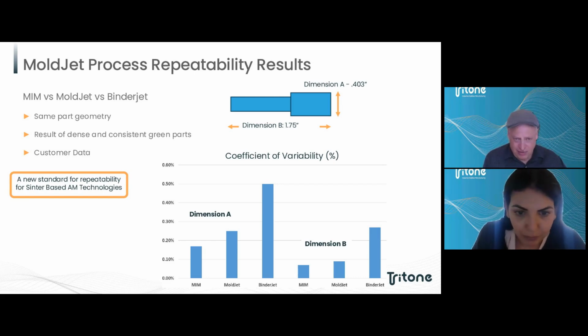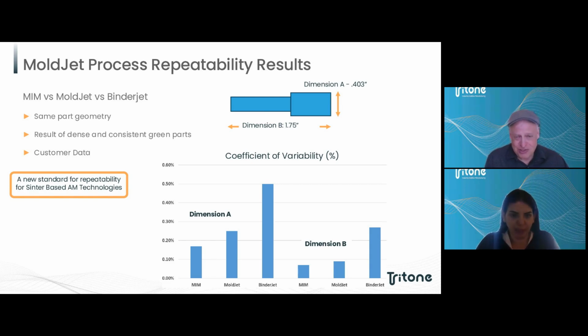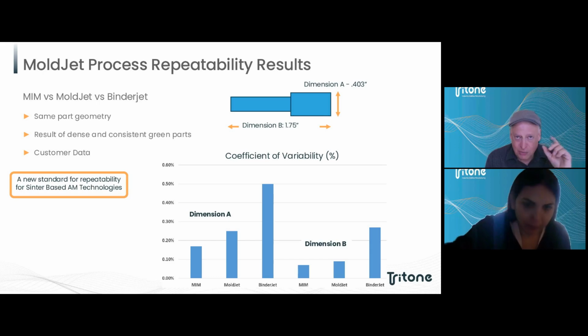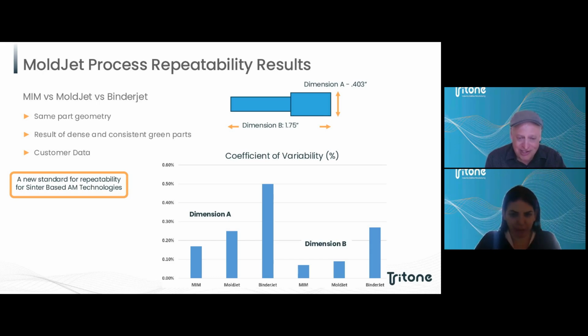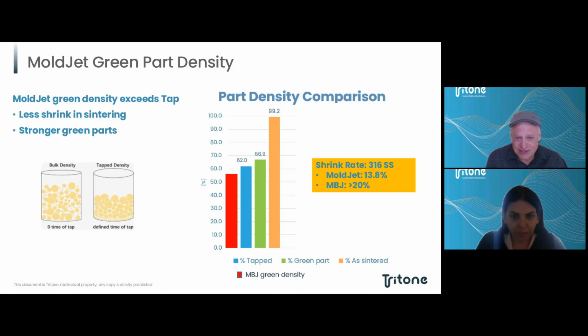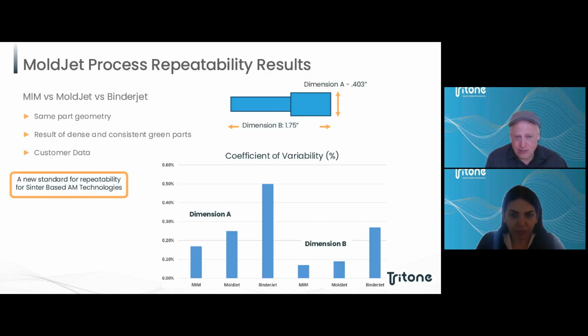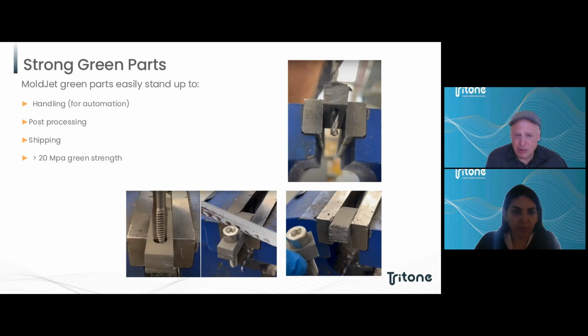It's a good point. Your timing is impeccable with that question because green part strength is another point. But the thing I want to say here is that it's easy to make statements like a highly repeatable process and strong green parts. What we're trying to show here is that there's a very simple, even easy to understand technical reason why we're able to make these claims. We're able to make claims about strong green parts and repeatability of results because of this. The higher density of the green part is what drives all of it. So that we get the repeatability, the strength of green parts, which allows for handling, right? It allows for automation of processes, allows for parts to be shipped if you want to outsource sintering.